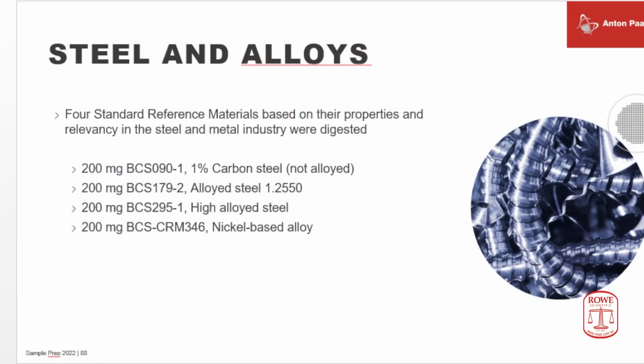Steel and alloys, we are still dealing with material testing. Also for this sort of materials we did tests with standard reference materials. Quite easy to digest, 200 milligrams. You do not need more because the samples are highly concentrated and they're very homogeneous. Digest simply with hydrochloric and nitric acid.